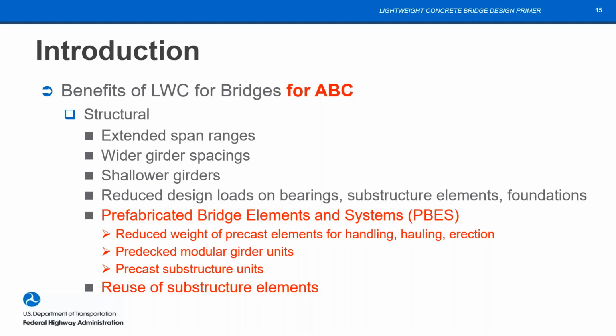And then even precast substructure units, which are oftentimes very heavy, can be made out of the lightweight concrete. One problem with precast substructure units is that oftentimes they may weigh as much as a long girder, but they're typically a whole lot shorter. So that can really pose some significant problems when you're transporting precast substructure units and meet load rating requirements on existing structures. And then the final bullet, again, is highlighted just since it is an important ABC strategy.